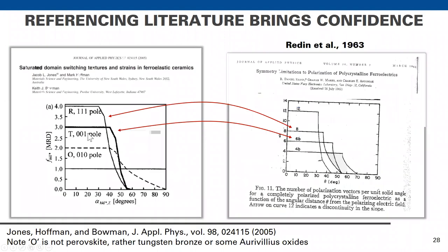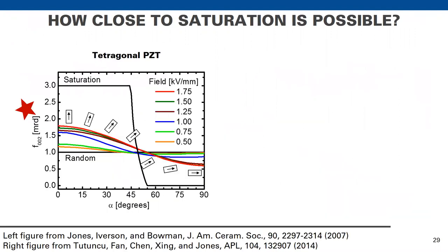Now, one needs to build confidence if you create models. And again, there's a thread of literature that informs what we're doing. And this one in particular was very nice. 1963, a paper by Redin in Journal of Applied Physics. And here you have complete analytical solutions to this. Okay. Now on the left-hand side, you're seeing our representation of the saturated pole figures for complete switching for the rhombohedral and tetragonal case compared to the equivalent ones calculated in this earlier paper. Okay. So this brings some confidence into the types of results that we're getting.